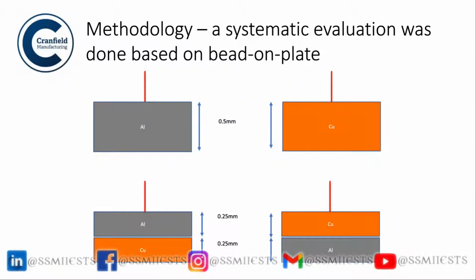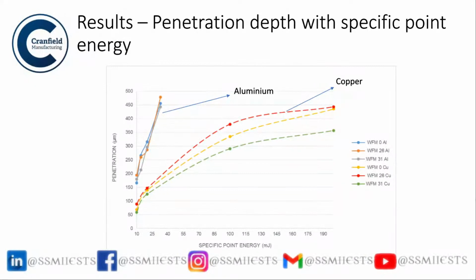So quickly, a very structured analysis was taken. Aluminium of 0.5 and copper of 0.5 were first studied as a bead on plate, just to see how much penetration happens. And then two aluminium 0.25 millimeter sheets were tested. Similarly with copper, and then aluminium and copper were tested as a dissimilar joint, to understand how the heat flows between the different joints.